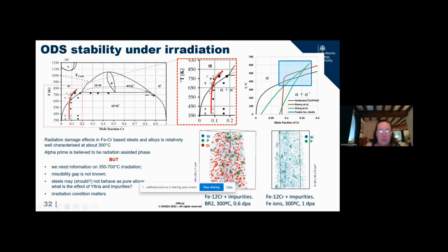What is tricky for us is on the phase diagrams that exist today, the solubility line, which takes us into the alpha prime phase, is very dependent on which of the scientists and which of the papers in literature you're looking at. And so if we could get some better handle on that solubility line, we'd understand a little bit more about how we might minutely control our composition so as to reduce the triggering of the alpha prime and the segregation of the chrome, because it's that segregation that is immediately harming the mechanical properties of the materials.